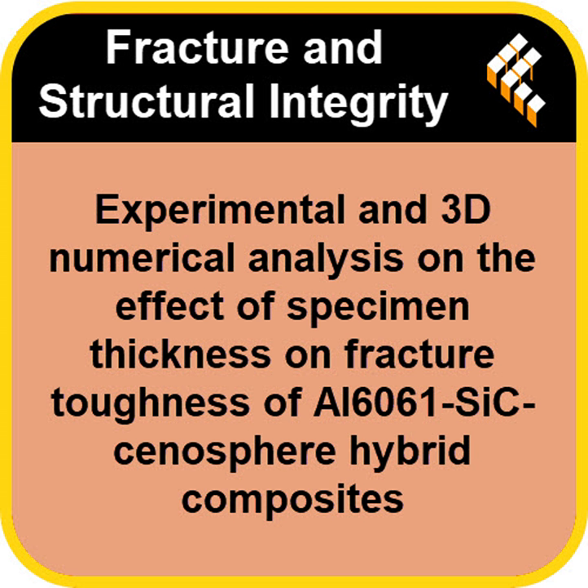Microcracks could form easily in the aluminum matrix and just zip right through, relatively unimpeded. Low fracture toughness. And the 6 wt%, what made that one special? The 6 wt% composite hit that sweet spot because the SiC and cenosphere particles were really well distributed. They acted as highly effective physical barriers. They literally forced the growing crack path to keep changing direction, to deviate around them. That takes more energy. It also helps redistribute the stress concentration at the crack tip, delaying the final fracture. More crack deflection, higher toughness.